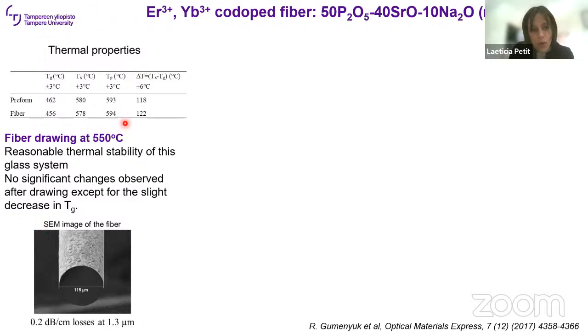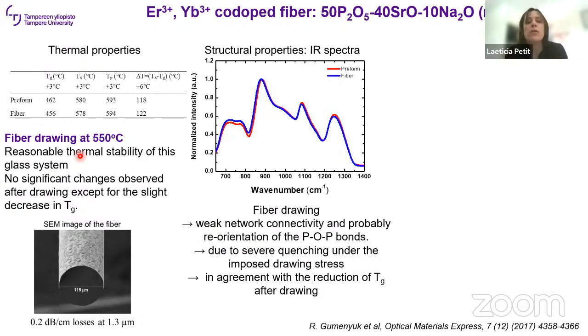We measured, of course, the thermal properties of the glass prior to and after the drawing, and we found a small decrease in the glass transition temperature after the drawing. We tried to understand this with the structure, so we looked at the infrared spectra of the glasses. In red is the preform, in blue is the fiber. We saw very small changes in the structure of the glass, as you can expect, because the drawing process is a fast thermal process, and it will induce only stress.